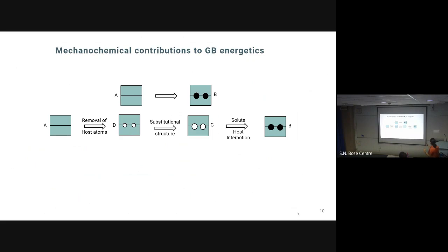when there will be this final structure where the solute elements will be moving there and replacing the host atoms, there will be chemical interactions as well as mechanical contributions. So there will be a misfit strain energy, and that is the most important aspect here. And this is how we are calculating. It is nothing but the energetics of the structure of B minus the energetics of the structure of A. That is how we are calculating the grain boundary segregation energy.